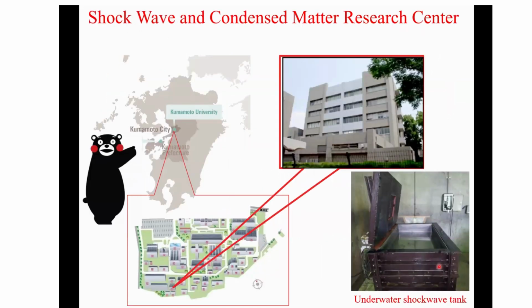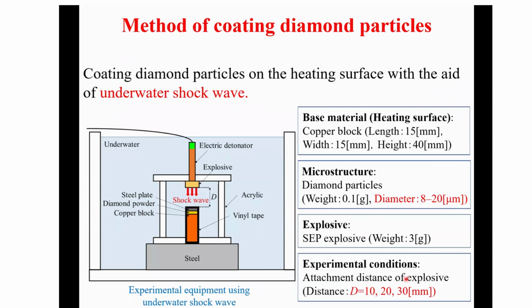At Kumamoto University, there is the unique Shockwave and Condensed Matter Research Center. This center is so unique because it can employ diamond. This is an underwater shockwave tank. This is a water tank, and this is a copper block. On this surface, very small diamond is collected, and with an electric detonation of the explosive, the particles are pushed and installed on the surface. The base material is a copper block, length 15 millimeter, width 15 millimeter, height 40 millimeter.